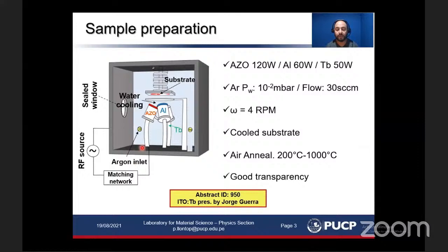The samples were prepared by radiofrequency magnetron sputtering. This is a schematic of the system used with these deposition parameters. The substrate holder was rotating at this frequency to obtain a good homogeneity between the samples. The substrate holder was actively cooled during the deposition, and I would like to emphasize this based on previous work in our lab.